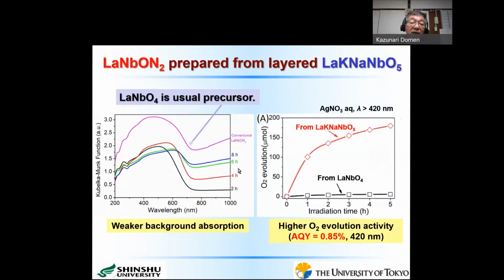Normally we use lanthanum niobium oxide as a precursor, but in that case, as you see here, the baseline absorption is very high. But when we use this lanthanum potassium sodium niobium oxide, after 2-hour nitridation, the baseline absorption is much lower. And when we compare the O2 evolution activity to these conventional starting materials, the O2 evolution activity becomes much better, and the apparent quantum yield was improved to about 0.85%.